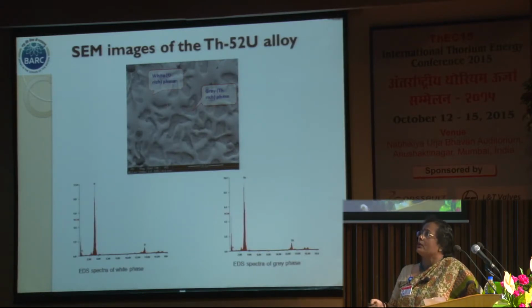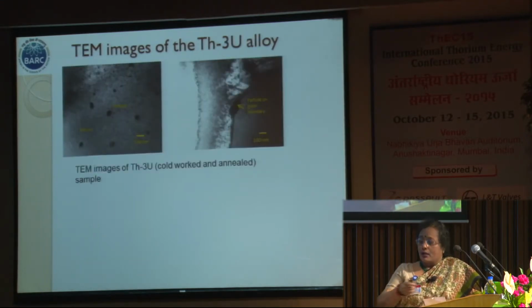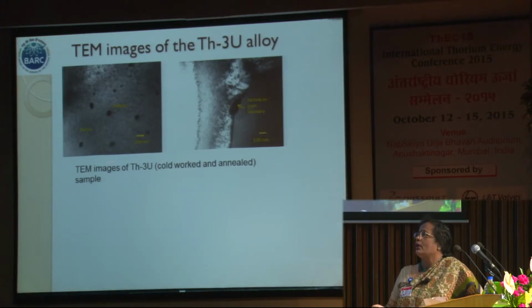This is the SEM micrograph of this thorium 52U alloy, where we did this analysis and composition certification was done. But in the case of lower uranium alloy, that is thorium 3U, here you could see a very good thing. When we did SEM, we could not trace the presence of uranium, so we went to TEM. Here we could see uranium is dispersed and the thorium matrix is in small globule form. Actually this is like a designed dispersion fuel. It is behaving naturally, getting dispersed, and we could observe that at the grain boundaries the concentrations were there very selectively.